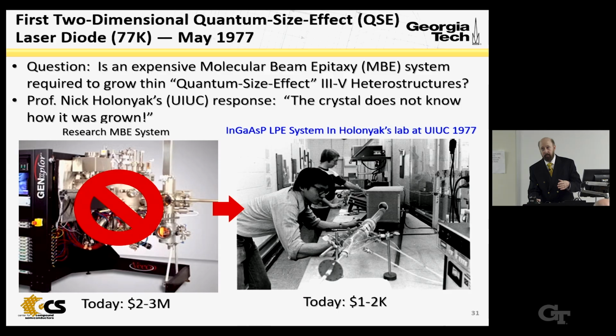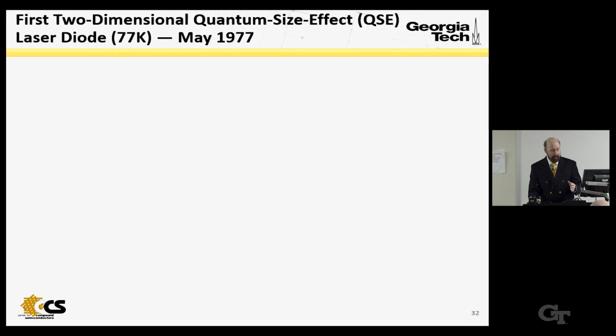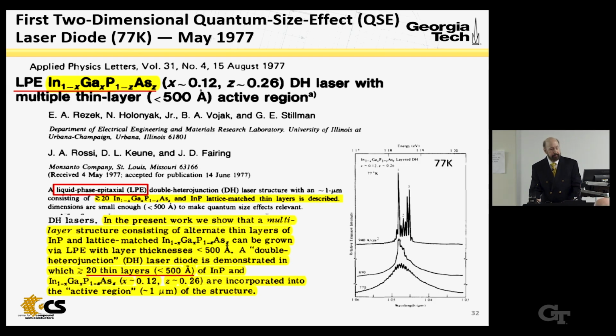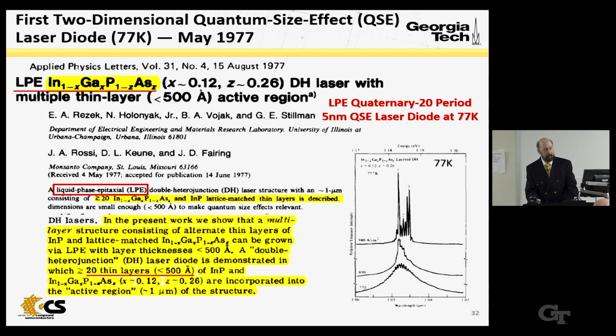Holonyak's team went even several steps further. They not only grew a trivial gallium arsenide quantum well, they grew a quaternary quantum well, a quantum well of indium gallium arsenide phosphide. I'm sorry, it's aluminum indium gallium phosphide. So here's their paper from 1977, the first two-dimensional quantum size effect laser diode operating at 77 Kelvin, pulsed again, and not CW. And you can see the spectrum here. This was an LPE quaternary 20-period quantum well with 5 nanometer thickness operating at 77 Kelvin. Again, this is infrared, so you see the wavelength's about 1 micron.